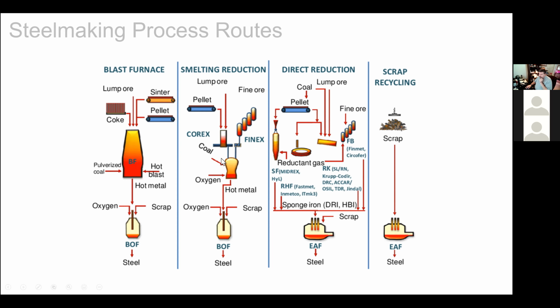And those materials get fed into this melter gasifier. The top gas comes off and it's very high in CO, so it's used as a reductant to pre-reduce pellets and lump ore before they're fed into the vessel. And the output of this is again hot metal that can go to a BOF, or it could potentially get fed to an electric arc furnace.